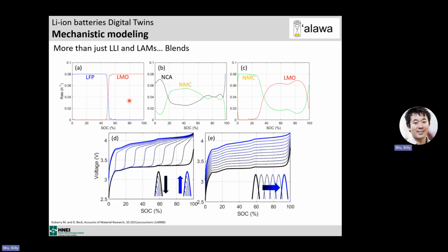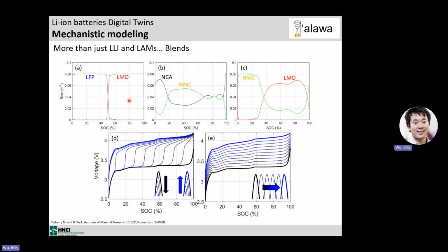We can also do blends, and I showed you that for plating, but we can do any of the blends. And what we added recently is to realize that in most models, when you do blending, you assume the same current on both components of the blend. But a really good group in Germany did some fantastic experiments to showcase that actually current density is not the case at all. It's not constant current in some cases. Yes, if you have LFP-LMO, when the voltage responses are completely separated, yes, it's constant current.